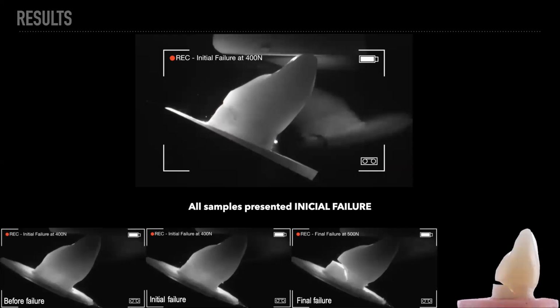So all the samples in this study present the initial failure because all of them receive a post inside the root canal. This initial failure, that is a wide gap between the crown and the root, occurs because of the elastic modulus, the elastic behavior of the post, that may be a disadvantage because of the cyclic bending between the crown and the core, and can induce micro cracks in the core and in the resin cement, leading to the failure of the restoration. Here we have one more movie about this initial failure that leads to the final failure of the restoration.